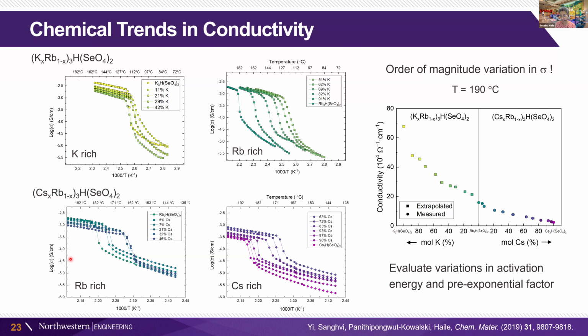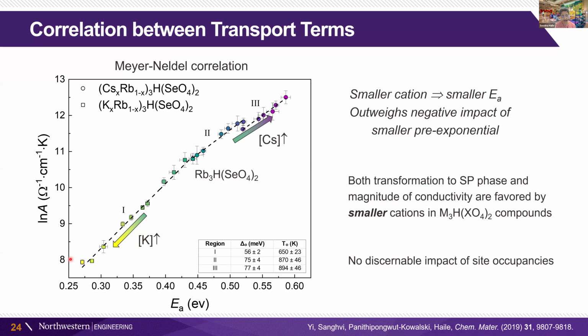So that's pretty significant. And it suggests to us that we could exploit a similar approach to improving the conductivity of our cesium dihydrogen phosphate. Let me just also connect this to something that's called a Meyer-Neldel correlation, which is a correlation between the pre-exponential of the conductivity and the activation energy. And these tend to be correlated in many instances and many phenomena.